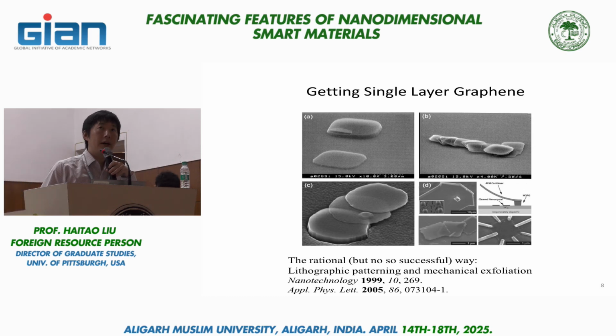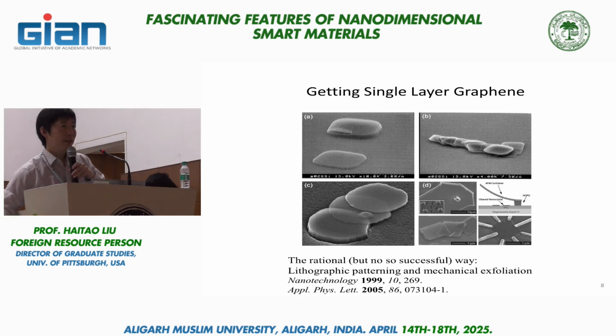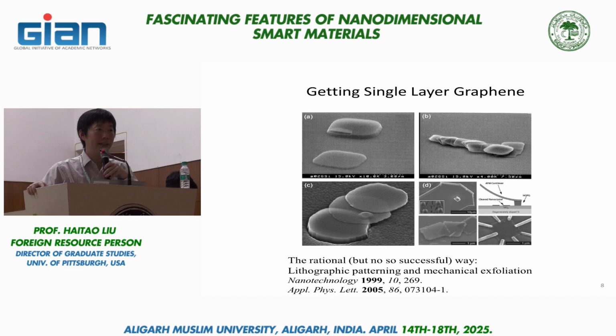What they ended up with were actually small chunks of relatively thick graphite pieces. Then there was another effort with a similar idea: they created small columns, and then came in with an AFM, atomic force microscope tip. Think about a needle. I have a column of micrometer-sized graphite, I come in and just bump it, hoping that I can get a single layer. Neither worked. It's a very rational approach: make a small column and then shear it until I get a single layer. But in reality, it doesn't work. They can get thin flakes, but they never got a single layer.